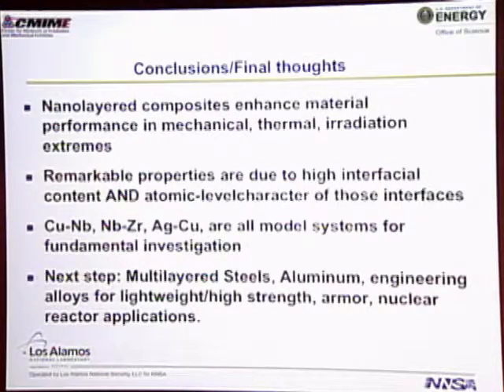So I'll go ahead and conclude here. What we found is that the nanolayered composites enhance material performance in mechanical, thermal, or radiation extremes. You can make damage-tolerant materials simply by putting them in these nanolayered architectures. We see that we get these remarkable properties that are due not just to having a lot of interfaces, but it matters what kind of interface you put in. What's the local structure of that interface?